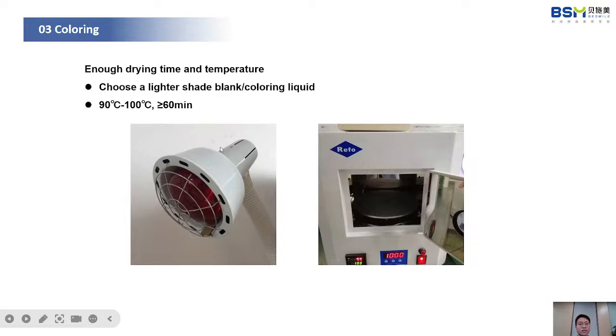So we can use those two small devices to do the drying. The drying time is more than 60 minutes for the full arch, and the drying temperature is about 90 degrees. If not, there will be some liquid inside the restoration, and during sintering, there will be a great risk of cracks.